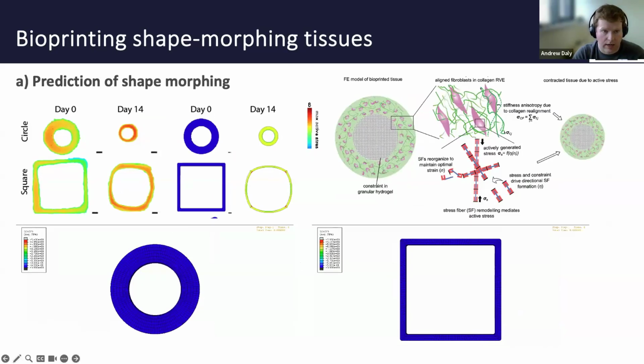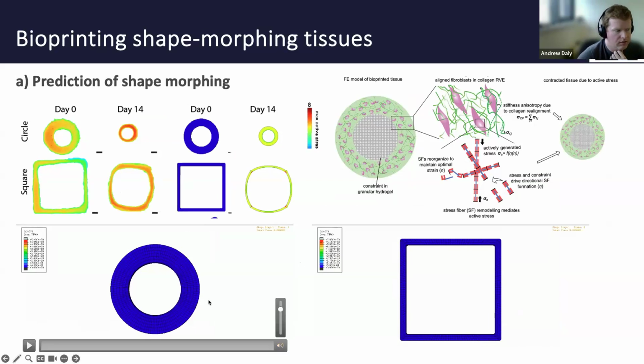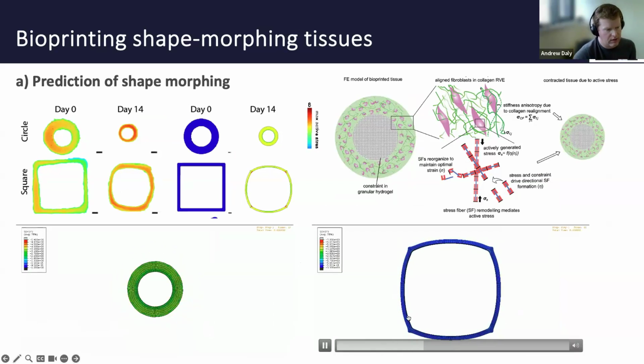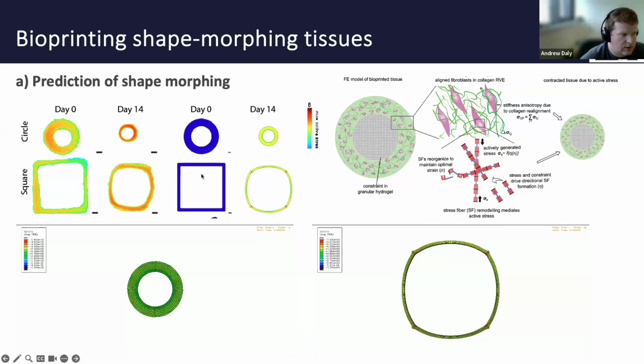We collaborated with another lab, the McGarry lab in biomedical engineering at the University of Galway, who are experts in finite element modeling of cell interactions with ECM. They've previously developed a model that can account for stress fibers pulling on collagen and the reorganization that happens over time in these tissues. And we were able to create models, these are just snapshot videos of this, that importantly predicted some of the experimental results we found. So we saw isotropic shrinkage of a tube, whereas if we initially had a square shaped structure, we got a different morphing pattern. The model is quite interesting because if we can predict it before we print, we can then use it to do an inverse design if we have a specific pattern we want to recreate.